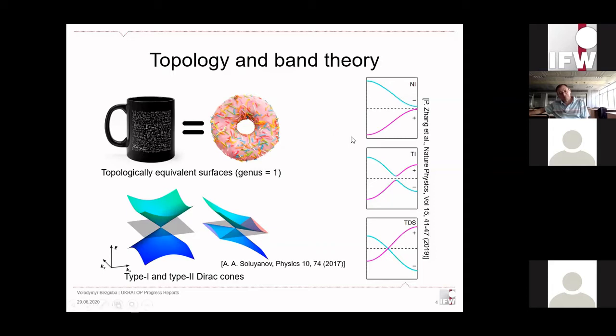For example, we can see some toy band structures on the right. If we consider the gap in a normal insulator and compare it to the gap in a topological insulator, in the case of a topological insulator we get a crossing of the gap, and in this inverted gap, topological surface states emerge, and thus this material becomes topological. This is interesting because it conducts current on the surface, but is an insulator in the bulk. The third case, the topological Dirac metal, is almost the same, only it is completely a bulk material and there is no opening of the inverted gap.